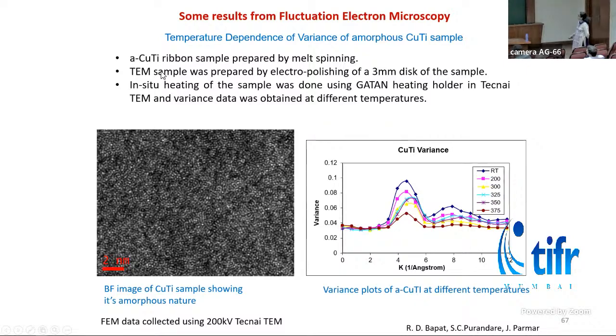So this is an amorphous copper titanium ribbon sample. It was prepared by melt spinning, and a TEM sample was prepared. The bright field high resolution TEM image shows that this sample is amorphous in nature. And this is the variance of the sample plotted with respect to K.